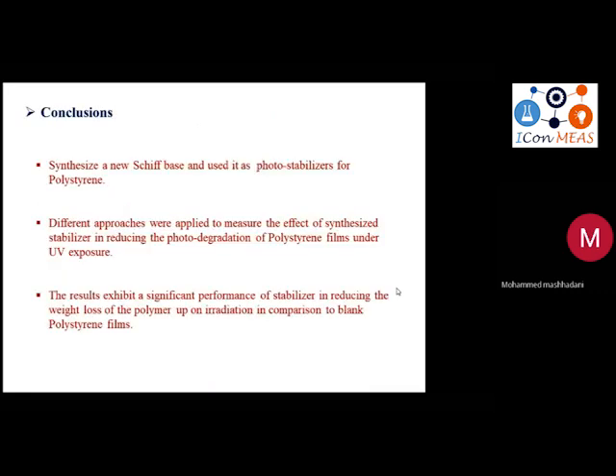Conclusion: we synthesized a new Schiff base and used it as a photostabilizer for polystyrene. We used different approaches to measure the effect of the synthesized stabilizers in reducing the photodegradation of polystyrene films under UV exposure. And finally, the result exhibited a significant performance for the stabilizers in reducing the weight loss of the polymer upon irradiation in comparison to blank polystyrene films.